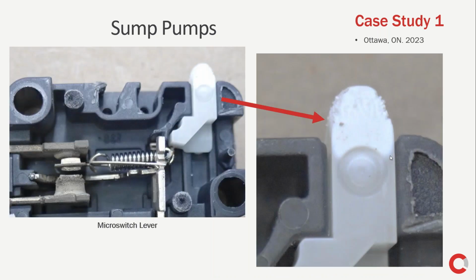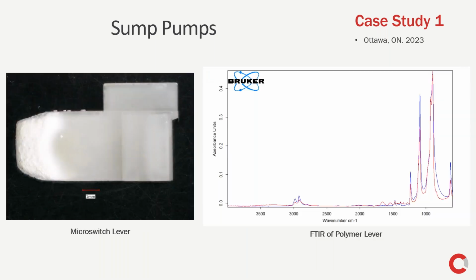So we opened the micro switch. You can see here clearly that that tab, or that lever, has been affected, but only the section of the lever that is outside the micro switch. Remember that this micro switch is inside the sealed float switch, but it's interesting that only that section of the lever is affected. So at this point, we obviously have to understand why that is in order to find the root cause. And so we did some analysis on that very tip that's discolored and damaged, as well as on the core of the material away from that damage.